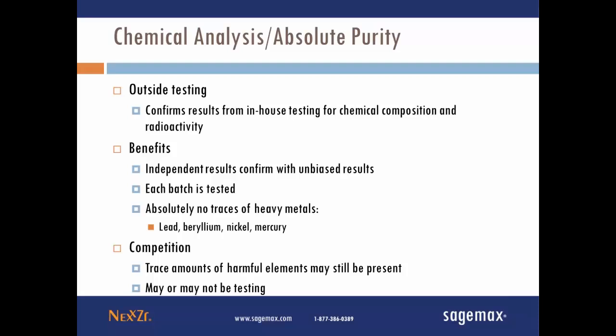And also there are no heavy metal traces in our material, namely lead, beryllium, nickel, and mercury, or any other destructive elements. And unfortunately what we see, because as I mentioned before, we do test all of our competition, occasionally we will see traces of some of these harmful elements, and we can't always be guaranteed that they are doing their own testing to prevent this sort of thing.